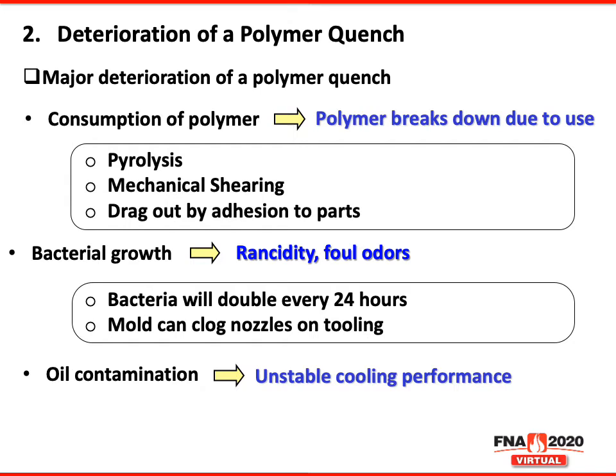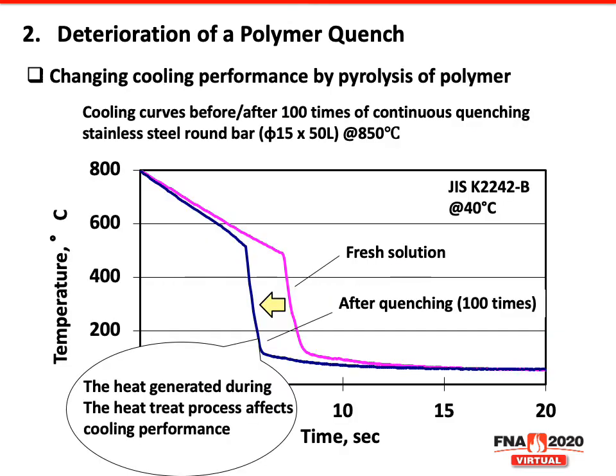It's also important to keep oil out, from hydraulic systems or any other types of lubricant, because that causes an unstable cooling performance. It's shorter than the original. Your nucleate boiling phase here, this slope becomes steeper than this, and as you move a cooling curve to the left, it becomes faster. So the performance of the product changes.